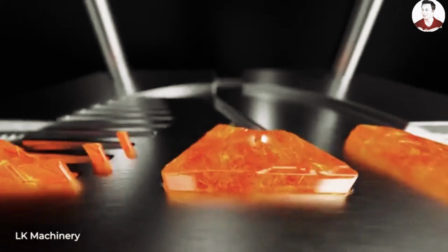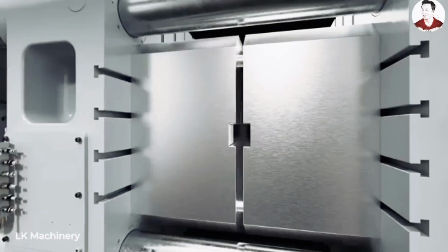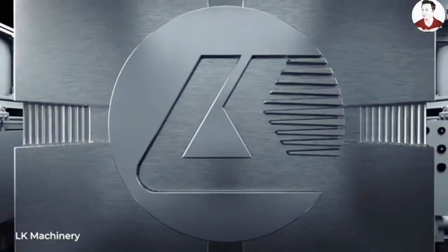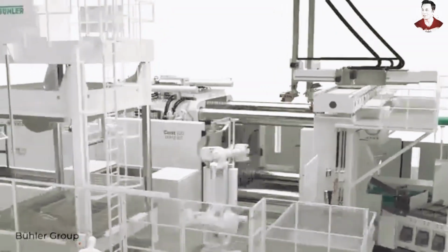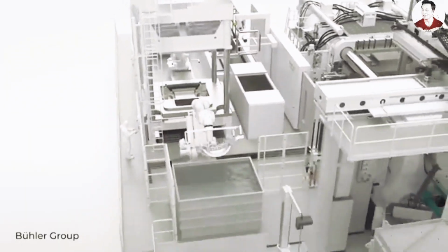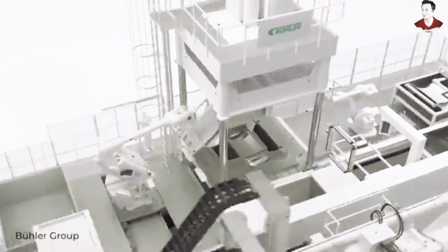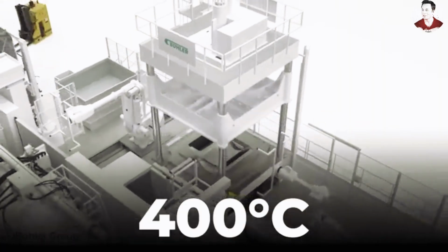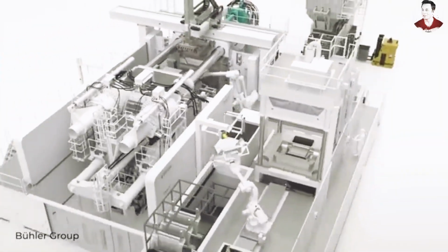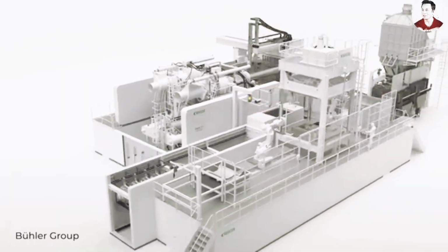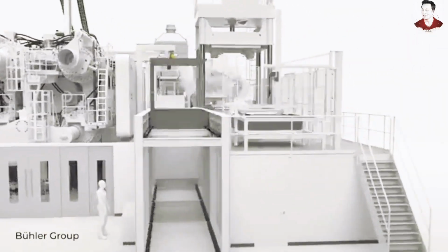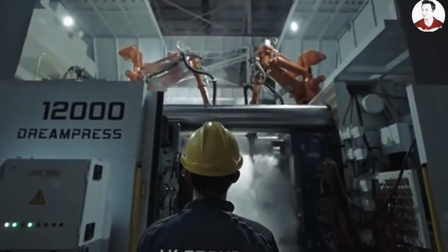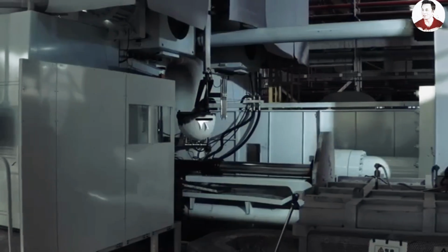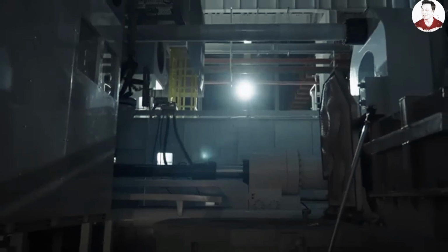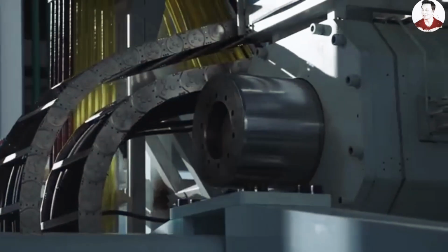Once the molten aluminum has been injected, the waiting begins, but only for a moment. The metal remains inside the mold just long enough to solidify before the newly formed casting is released at an astonishing temperature of nearly 400 degrees Celsius. Even then, the process is far from over. The glowing hot casting is immediately transferred into a cooling bath, where its temperature plunges from roughly 400 degrees Celsius to about 50 degrees. That rapid cooling isn't just about speeding things up, it also helps eliminate certain casting defects while improving the material's overall mechanical properties. Meanwhile, the mold has its own reset sequence. After opening, it's cooled to around 185 degrees Celsius before a robotic system thoroughly cleans every surface, ensuring it's perfectly prepared for the next shot.